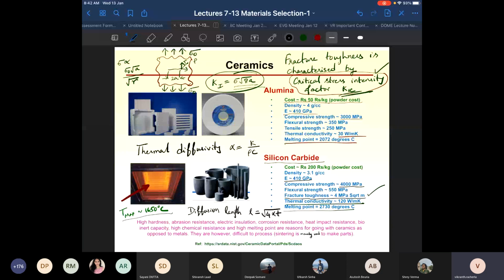So using something like silicon carbide or alumina ceramic tiles, you get a couple of advantages. One is their density is lower. So for the same volume, the mass of these armor plates would be lower. And second thing is they have very high melting points. So the heat which is generated during that impact is not going to soften the material. And third, they have very high compressive strength.